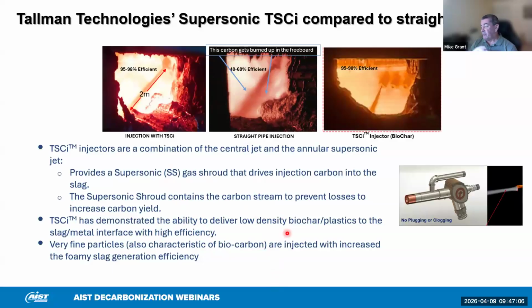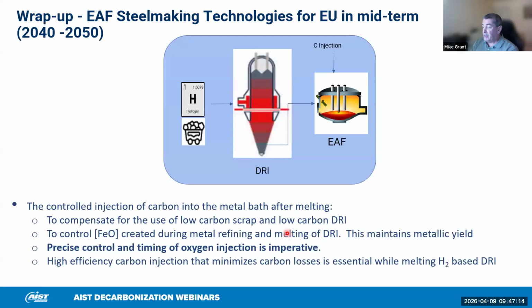The more efficient you have, the more you can control it, the more you know how much carbon you're putting in the system, and you can balance that with oxygen. So just to wrap up, with hydrogen-based DRI, we demonstrate, at least on the theoretical level, it's effectively the same as high carbon 96% metallized DRI. And the question is how do we control the carbon and how do we control the oxygen so that we don't lose too much of our iron in the form of FeO.